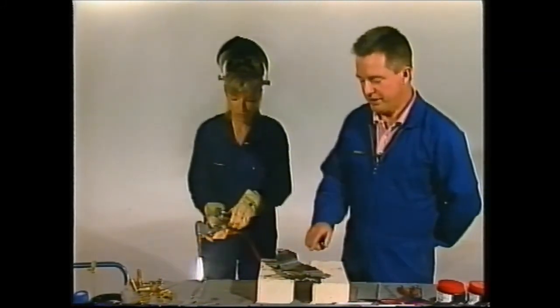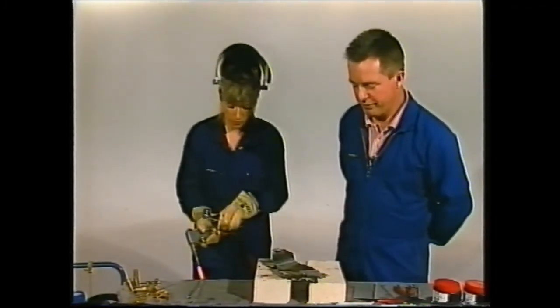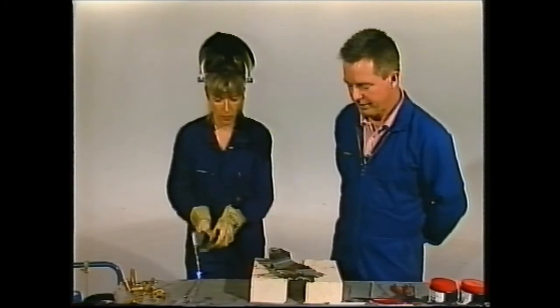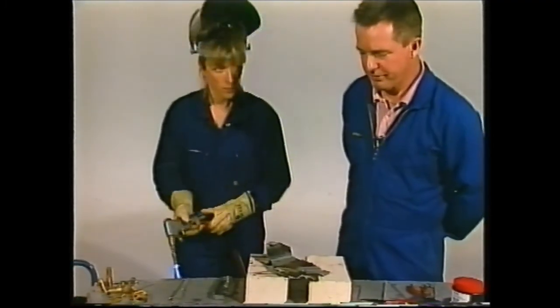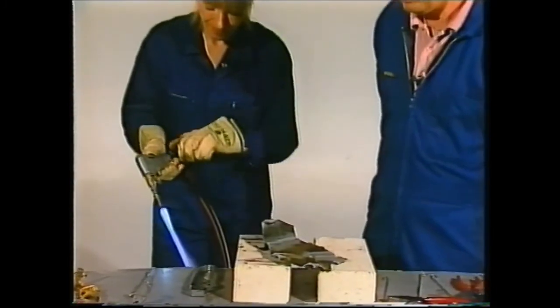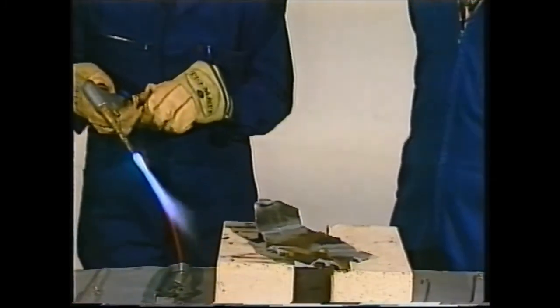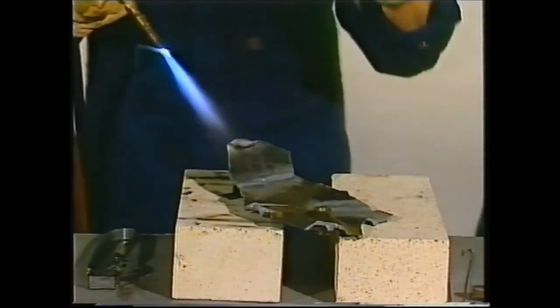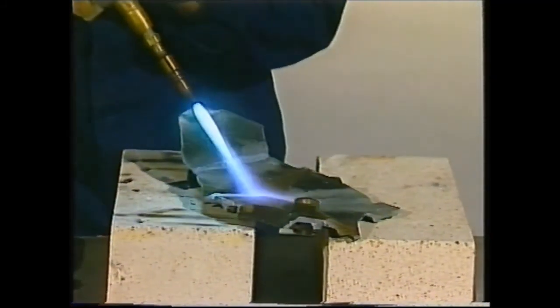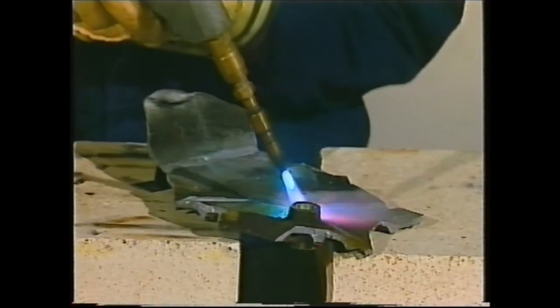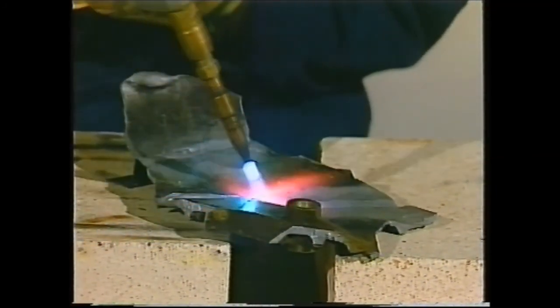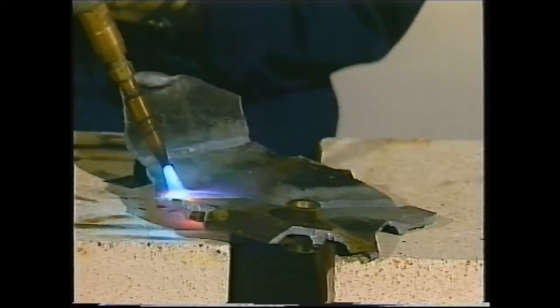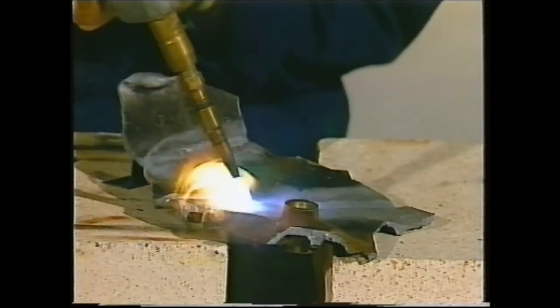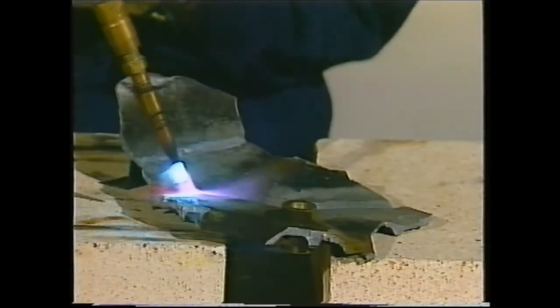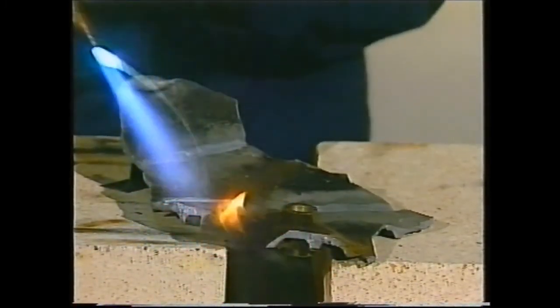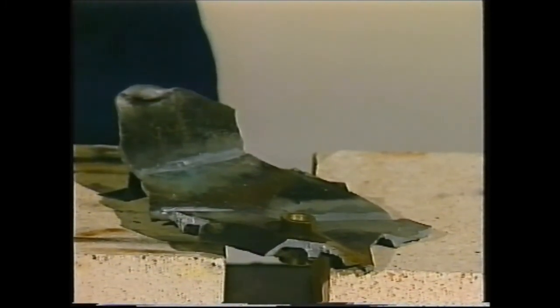Now we're going to be using here just standard 4043 filler rod, and just again a slight bit of flux on the rod. Okay? Now what we'll do, the procedure is to just make the surface just barely move, turn the torch up slightly, and you'll just get the surface to crinkle. Once it's moved, you then turn the torch down to do the actual weld. But unlike a conventional oxy torch, the whole thing doesn't all collapse into pieces on you. Now you see the surface just started to move then,